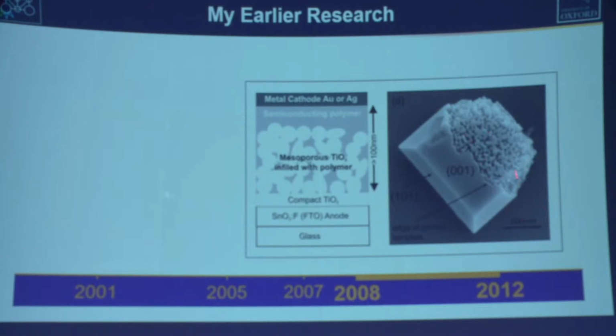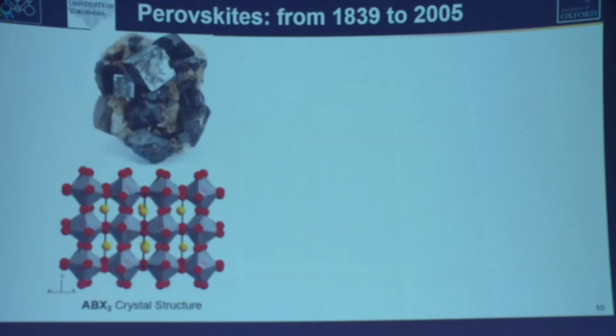The really interesting aspect of this material is you have single crystal-like electronic properties, but you have the high surface area you need from the porosity. This was really exciting. I personally thought we found the perfect porous material. This was in 2012, just before what I'm about to present you came along.